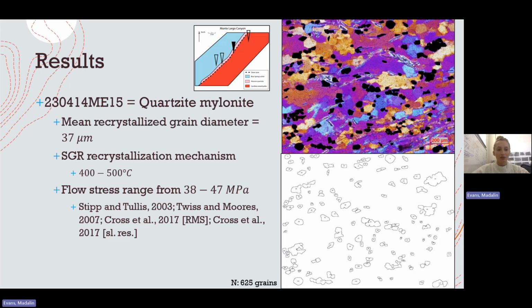The 15 sample is the quartzite mylonite sample, and that had a mean recrystallized grain diameter of 37 microns, and it also had a subgrain rotation recrystallization mechanism, meaning that it also had a temperature range between 400 and 500 degrees Celsius. Now, regardless of the similarities between this sample and the last, this one does have evidence for mylonitic foliation, which corresponds specifically to the shear zone. The flow stress range for this one is between 38 to 47 megapascals.